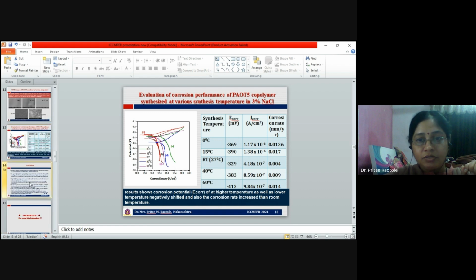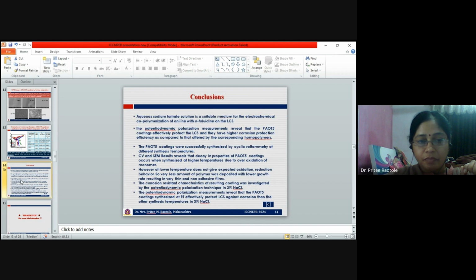Now the conclusions of the present work are: the aqueous sodium tartrate solution is a suitable medium for the electrochemical copolymerization of aniline with O-toluidine on low carbon steel. The potentiodynamic polarization measurement reveals that the PAOT5 coatings effectively protect the low carbon steel, and they have higher corrosion protection efficiency as compared to that of the corresponding homopolymers.